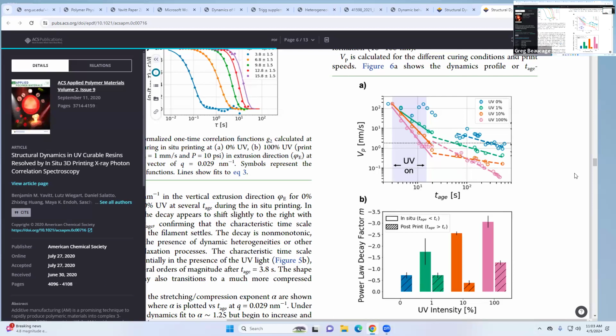And that's going to be a big consideration when you want to put another layer on top. You're going to disrupt that structure, and it's going to evolve in some new pathway as well, right? So I think these experiments were interesting because we were able to define that time scale. I think it was 10 minutes in between filaments when we started to see it equilibrate. So technically you'd have to wait 10 minutes between printing one layer and the next to get a real true equilibrium part, which no one is going to do. So that was the second project we did.